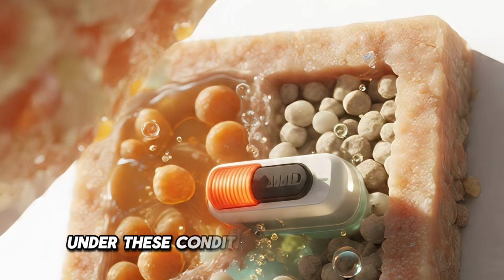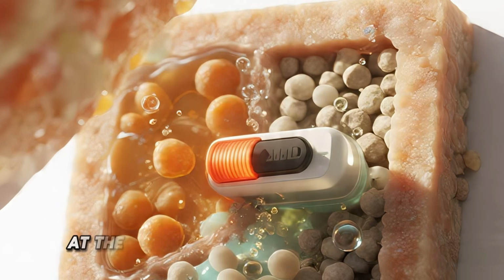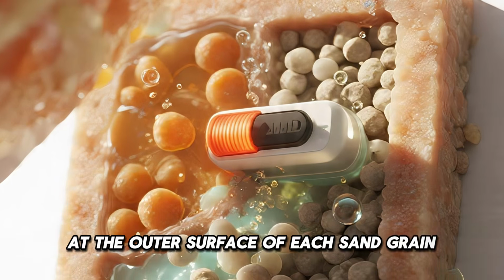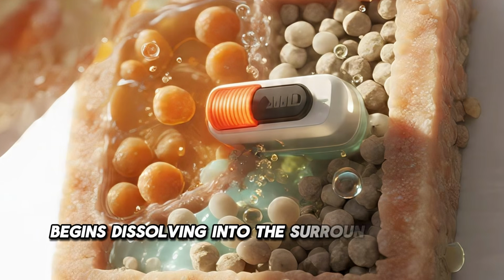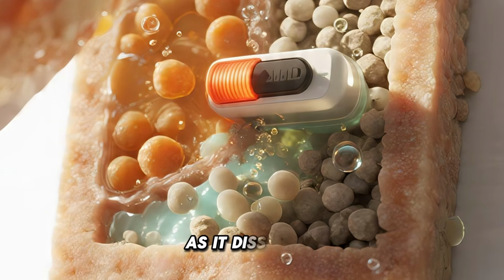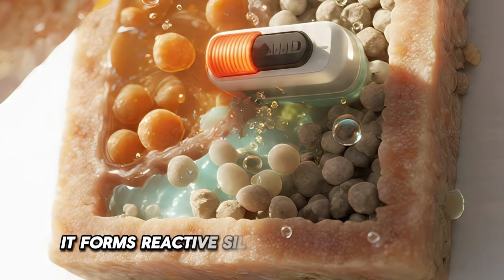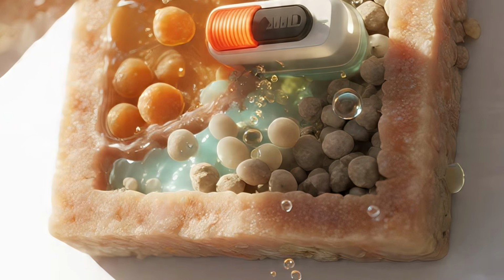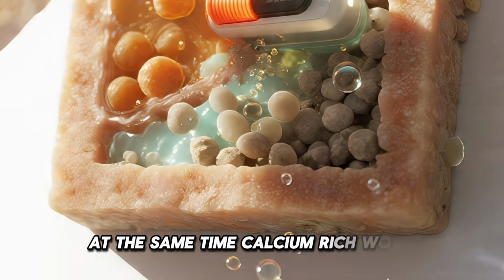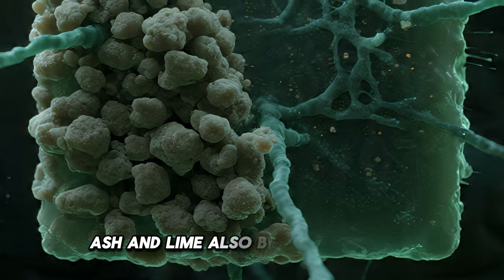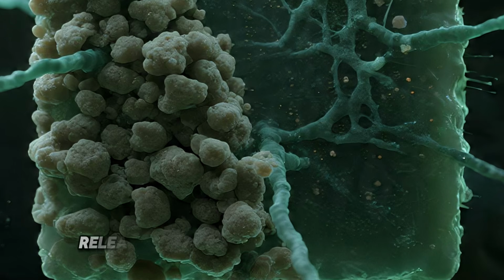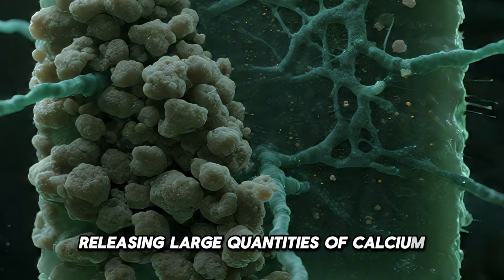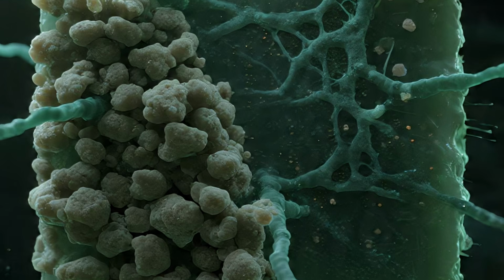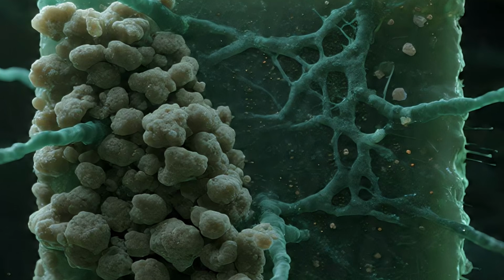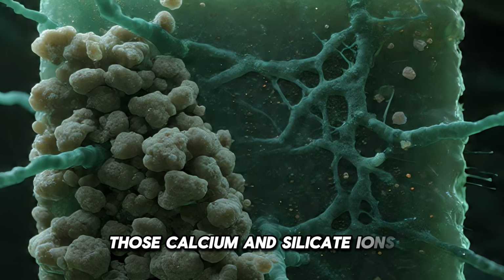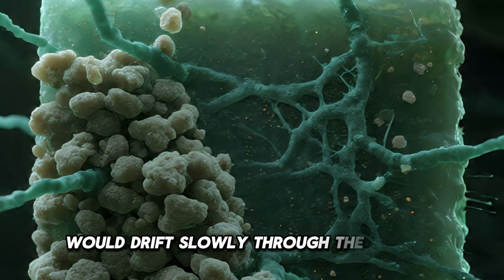Under these conditions, amorphous silica at the outer surface of each sand grain begins dissolving into the surrounding pore water. As it dissolves, it forms reactive silicate ions in solution. At the same time, calcium-rich wood ash and lime also begin to dissolve, releasing large quantities of calcium ions into that same water.